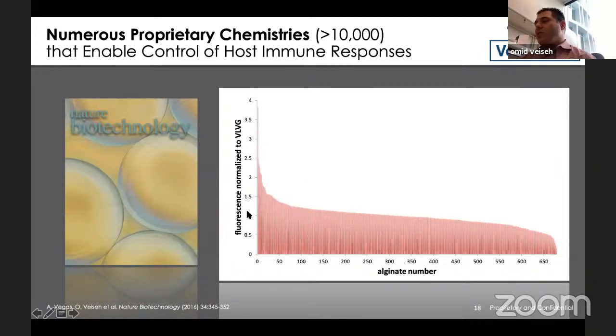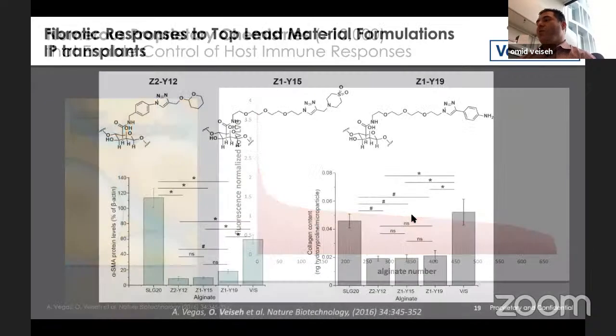One of the things that you notice is the base material, which is the unmodified alginate, produces a particular fluorescence response that we set at 1. And we noticed that many of our modifications actually exacerbated the immune response much more significantly. But we were excited about these formulations down here, which were materials that actually did not provoke much of an immune response at all. And so we wanted to learn more about what those are.